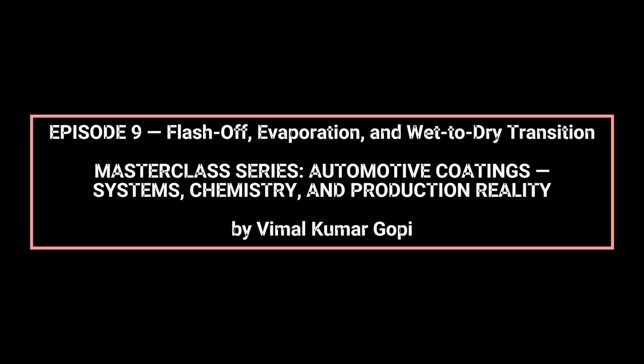Flash-off is not optimized for perfection. It is engineered for stability under variability. In summary, flash-off and solvent evaporation control the entire wet-to-dry transition in solvent-based automotive coatings. They determine leveling, metallic orientation, surface texture, solvent release, and long-term durability. Mastery of flash-off behavior is essential for translating laboratory success into OEM-approved, production-stable coating systems.